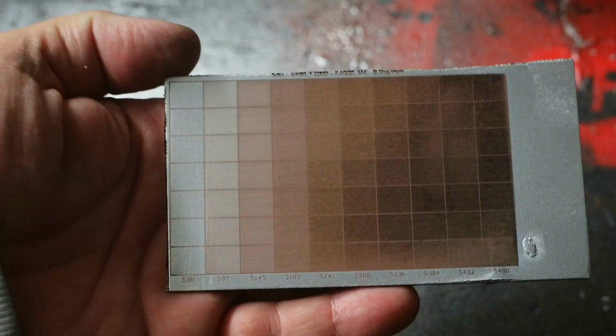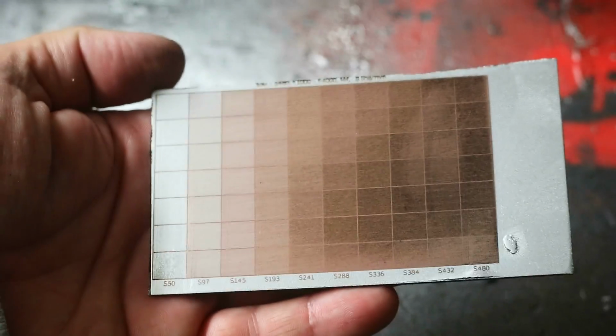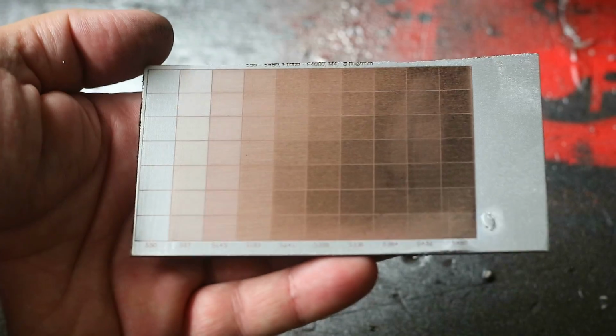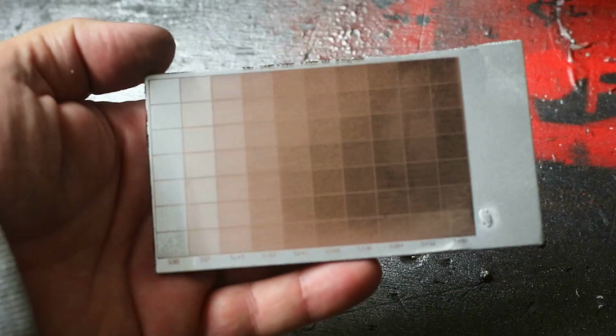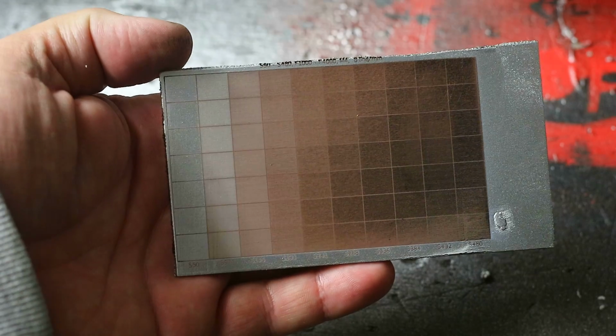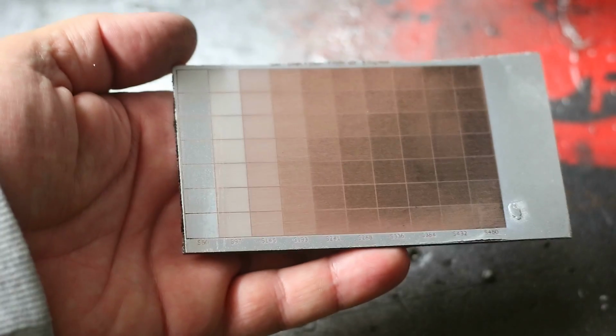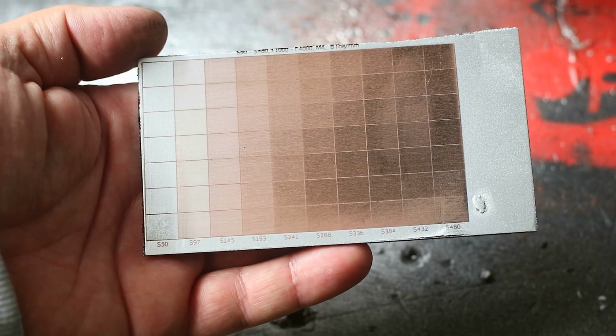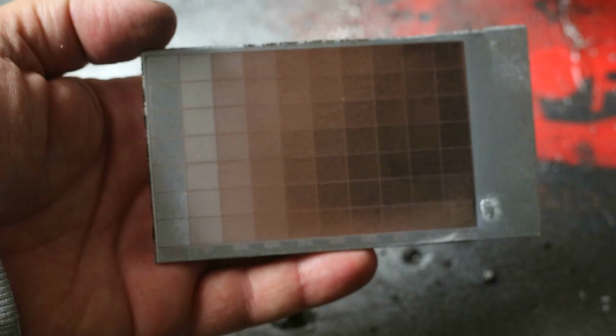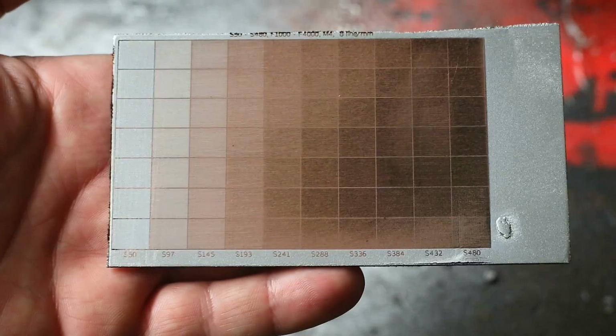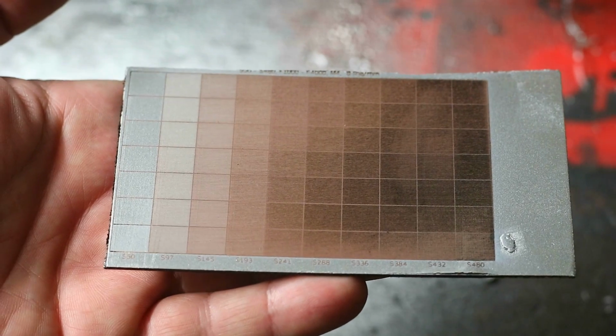So I sprayed it on, let it wait no more than 10 or 15 minutes to dry, and then burnt another one. And you can see with this silver paint, I've still got black coming out. And it sort of explains the mystery behind the first test I did with the black area where it should have been lighter. It's because the paint itself is just disintegrating, it's just burning. So the black areas you can see on the silver one is this burnt paint.